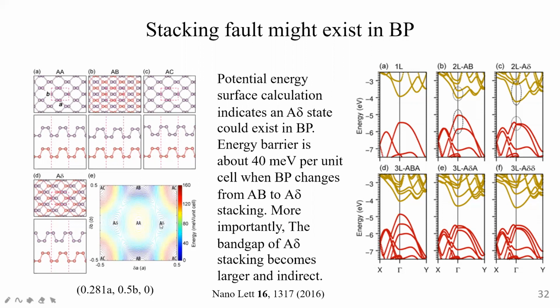This state is metastable, and it could also exist. The energy barrier from AB stacking to A-delta stacking is 40 millielectron volt per unit cell. So this state could happen.